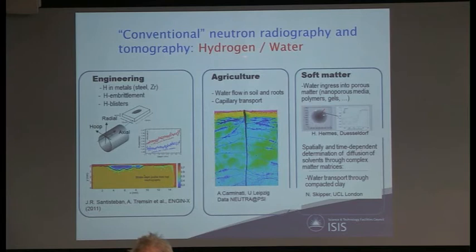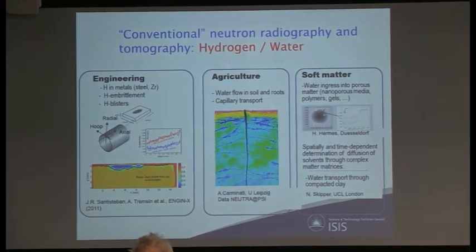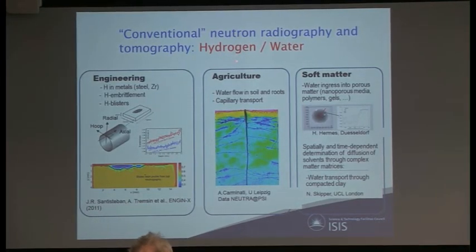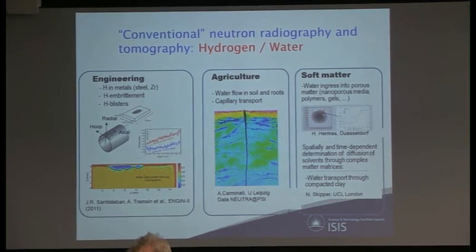And that brings me to the other important point: localization and determination of hydrogen distribution. We will certainly use the beamline to determine diffusion coefficients and hydrogen distributions in metal alloys and steel, zirconium, to look at effects like hydrogen embrittlement, and measure the extent and locations of hydrogen blisters.